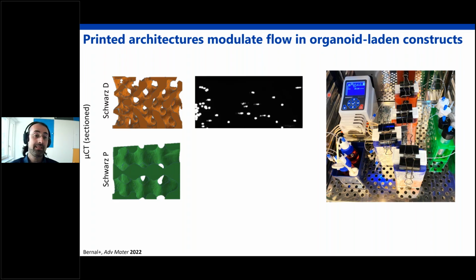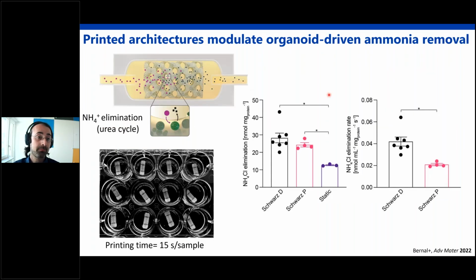And we tested how this can affect functionality of the organoids by perfusing ammonia into the system. What the liver normally does in our body is take ammonia and convert it to urea, which is then eliminated by the kidney, and ammonia is toxic, of course. And we see indeed how playing with the geometry, especially the more tortuous parts, helps the organoid to eliminate ammonia faster, so therefore to detoxify the compounds at a much higher speed, which is beneficial then to make a more relevant liver model that can then be used for testing new compounds.